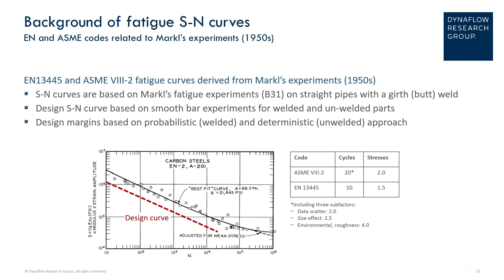It is important to note that this is not a real safety factor; it is only meant to include the effects that were not measured by Markle's experiments. Some of these effects are data scatter, which includes a sub-factor of 2; the effect of size, which includes a safety factor of 2.5; and any environmental or roughness effects, which includes a safety factor of around 4. When multiplied together, this forms the safety factor of 20 on cycles seen in the ASME code.